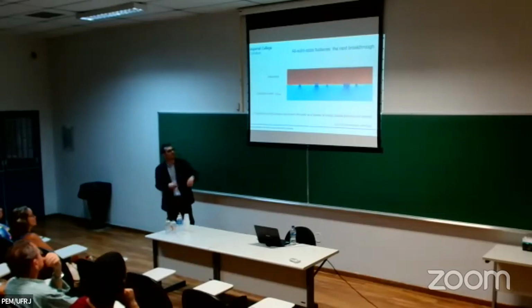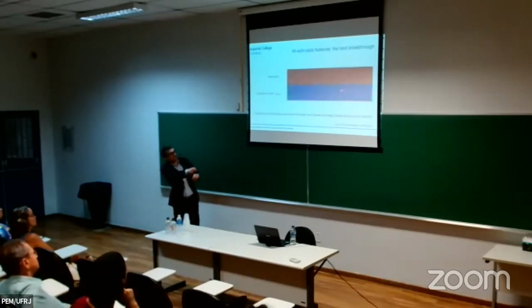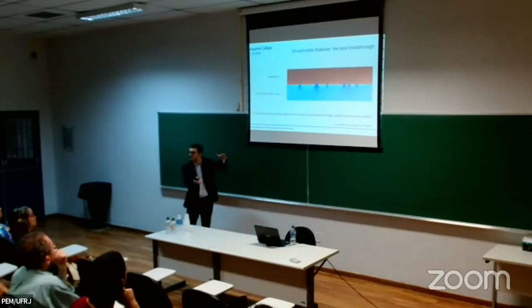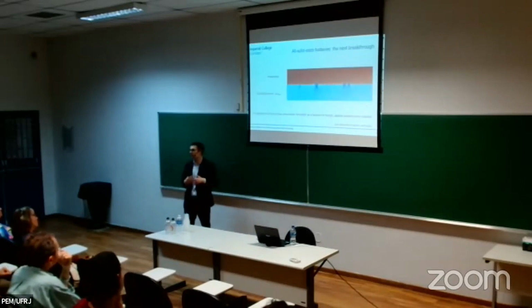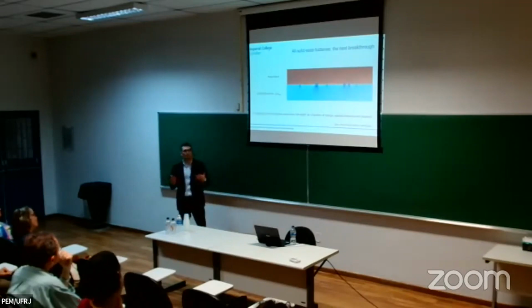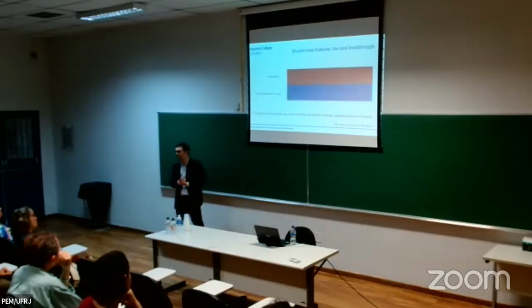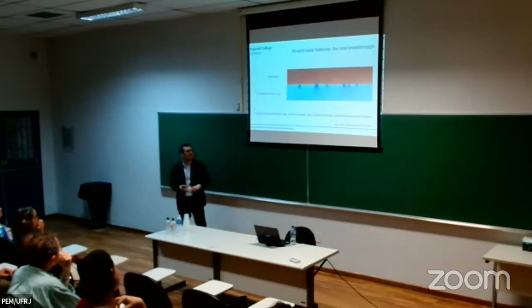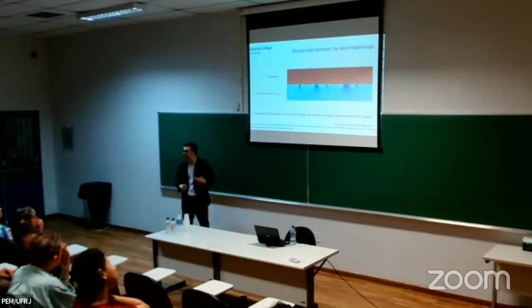And we can do this, of course, for much more, I would say, technologically relevant conditions where we have multiple charge and discharge cycles, where we have multiple voids that interact with each other. We're doing this at the same time as we apply pressure, so we're able to capture how those voids eventually shrink and at which pressure we will make those voids disappear. So effectively, again, the takeaway is that we have a virtual platform that allows us to map what are safe regimes of operation, what are the regimes that will enable a breakthrough in this solid state battery technology. We can predict this voiding and hotspot phenomena as a function of the pressure, of the material, of the geometry of the cell, of the mold, the material of the electrolyte and the anode, and so on.